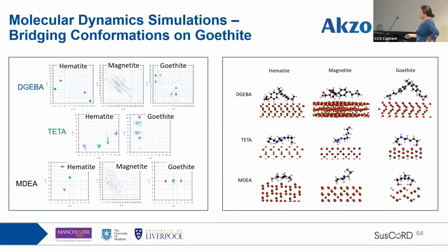So we think that binding is so favourable that it drives the molecule to sit in this unfavourable bridging conformation. And that's happening with the polymer as well. This same driving force is pushing the polymer to adopt certain configurations, limiting molecular mobility, segmental mobility, and giving us that increased TG as a function of the pigment volume concentration.